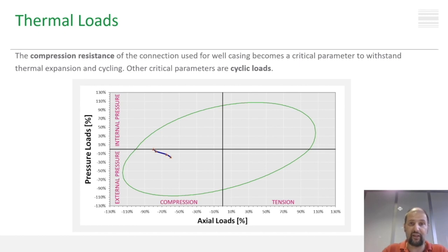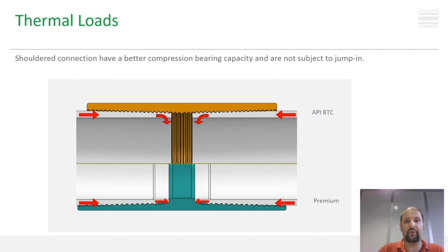For working string analysis, we typically use state-of-the-art commercial software such as StressCheck and WellCat. On top of this, for geothermal wells, it's common to perform strain-based design, such as the Holliday modified method, cold collapse, and short buckling. For this analysis, we typically use proprietary software. Given that compression is an important load mode for thermal wells, here we see a comparison of different connection technologies, a buttress and a premium connection, and we analyze the different compression load bearing mechanisms.